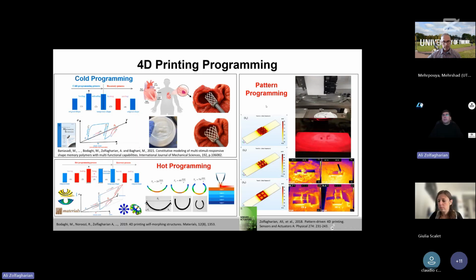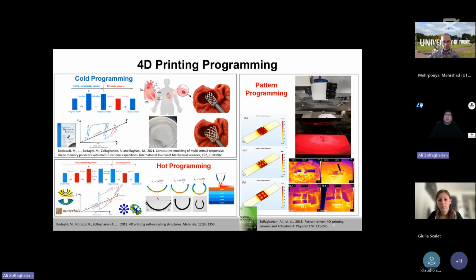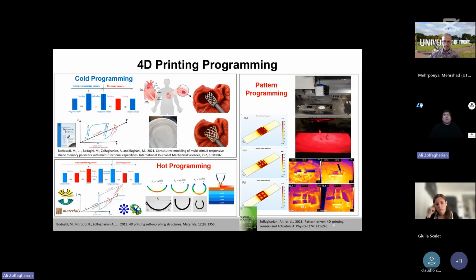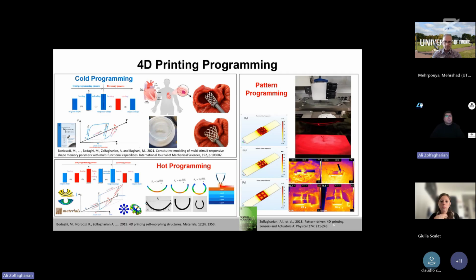For example, on the right is pattern-driven 4D printing, printing different patterns on a pre-strained polystyrene sheet. We could achieve bending and then control the bending using specific 3D printing parameters. Then we came up with cold programming, where we use printing process parameters like the velocity and the temperature of the nozzle and bed to print something, then apply the loading at room temperature or below the Tg, and then by applying the Tg, we could harness some sort of bending.